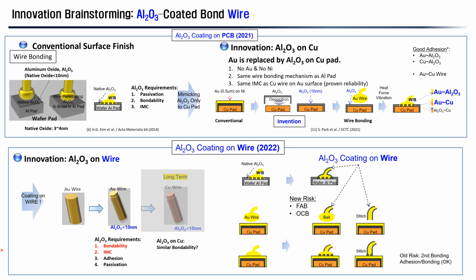In the past, we have seen a good bondability with aluminum oxide. Aluminum oxide does not interfere with the first bonding and the second bonding, in the same way as the aluminum oxide coating on PCB copper pad before. You're seeing a gold wire bonded to the aluminum pad. We introduced aluminum oxide coating on bond wire. There's no interference. And you're seeing a conventional bond wire bonded to the PCB copper pad. Here's the aluminum oxide coating. There's no interference. Looking at the second bonding, there's no interference as well.